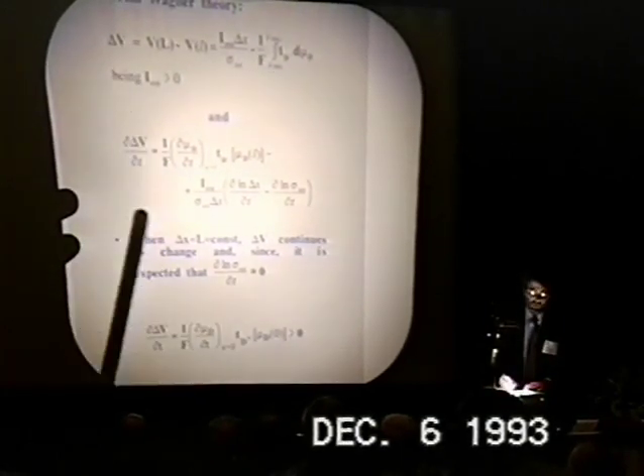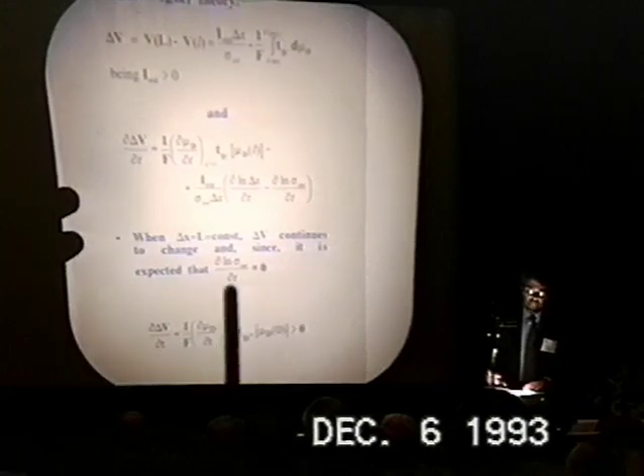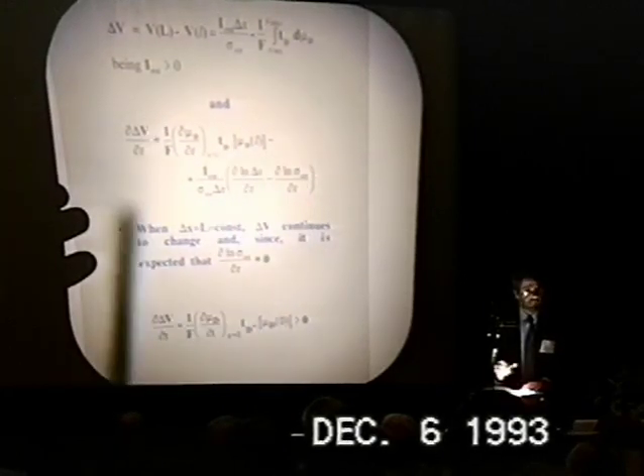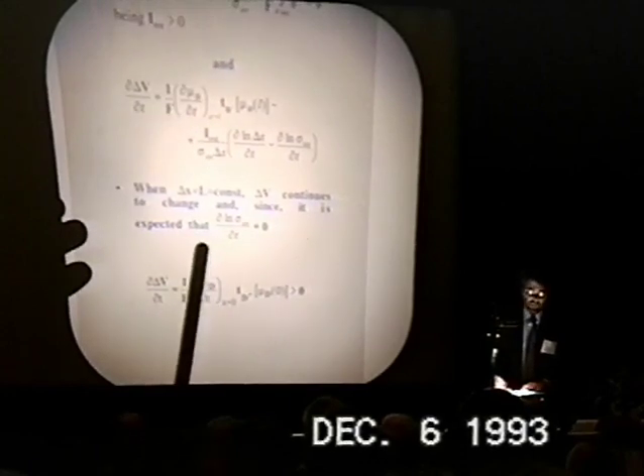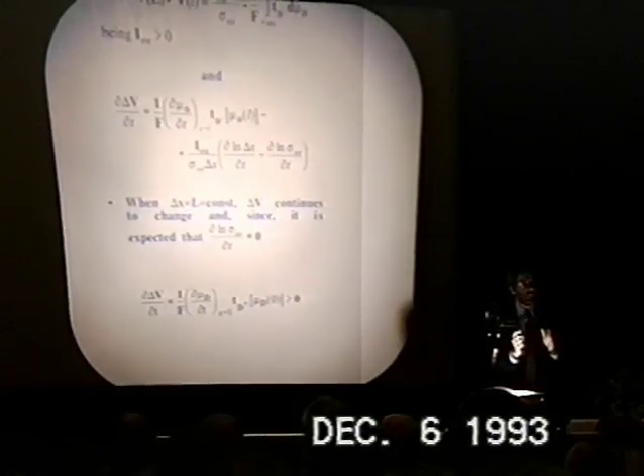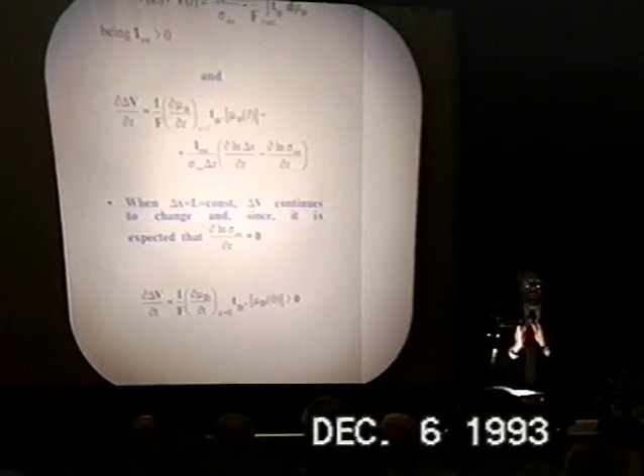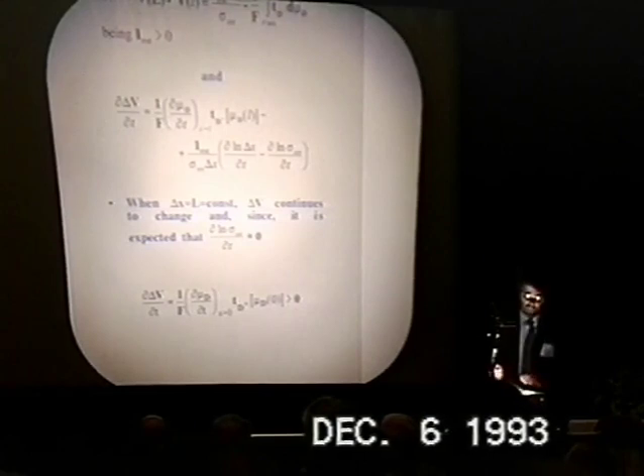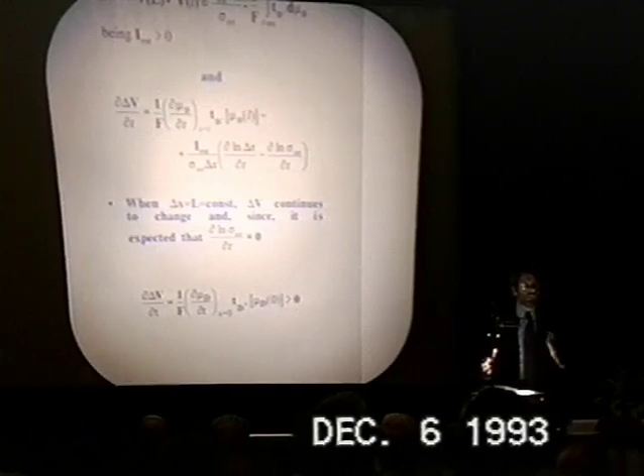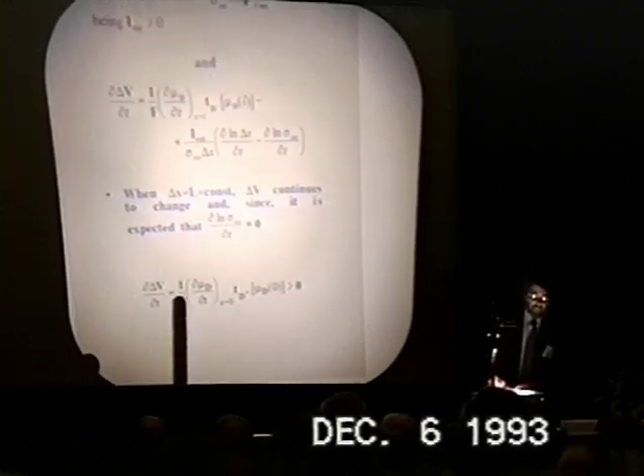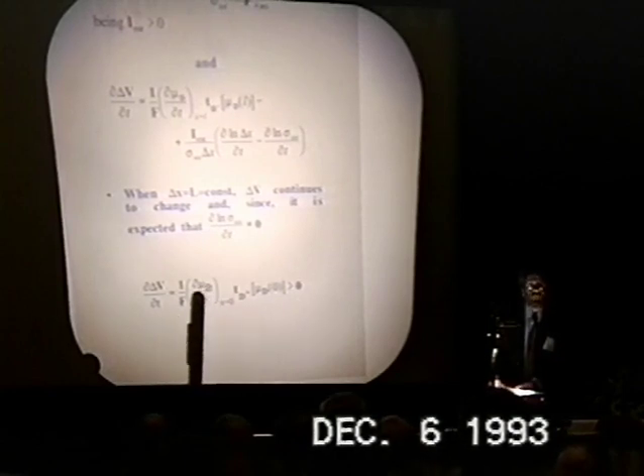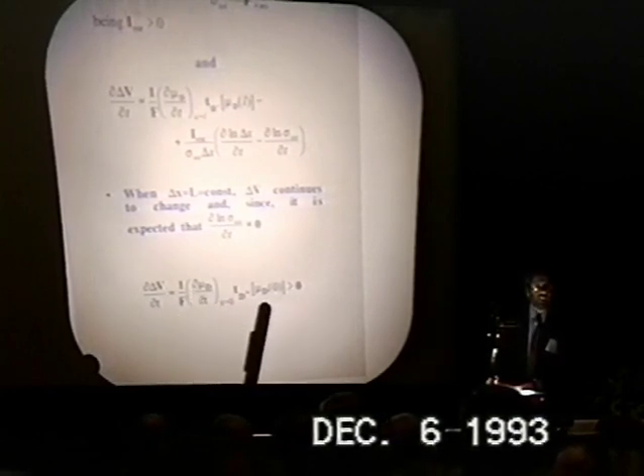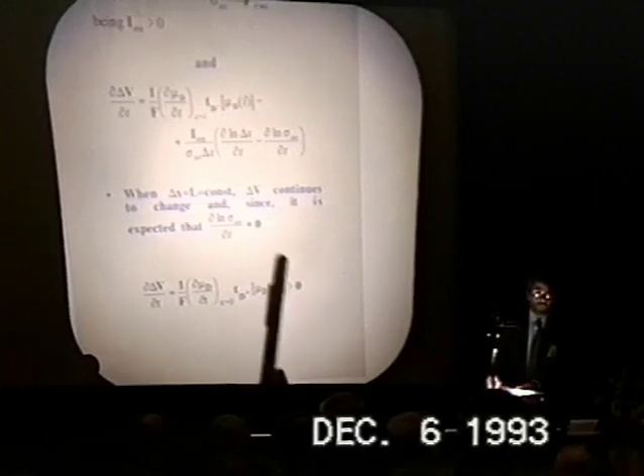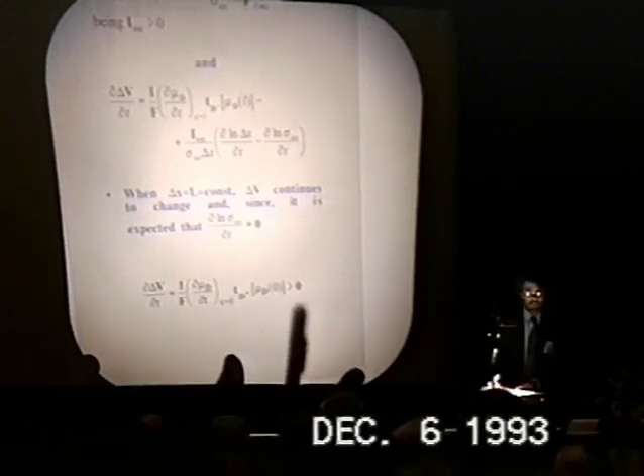The dependence of this voltage drop on temperature is related to this quantity. But a very important conclusion is that when delta x, the thickness of the layer, becomes constant, equal to the radius of the cathode, we have a situation in which the voltage drop continues to grow, and this depends on the derivative of the chemical potential and the ionic transference of deuterium. This quantity is always positive.